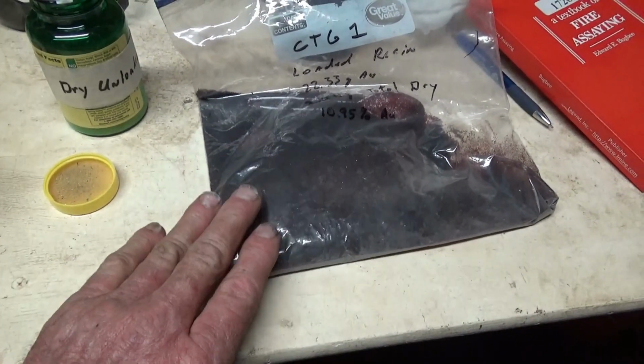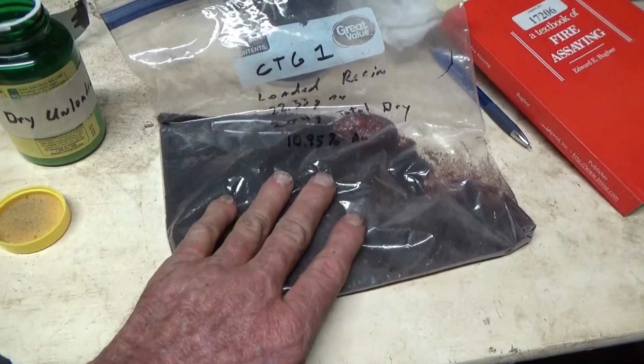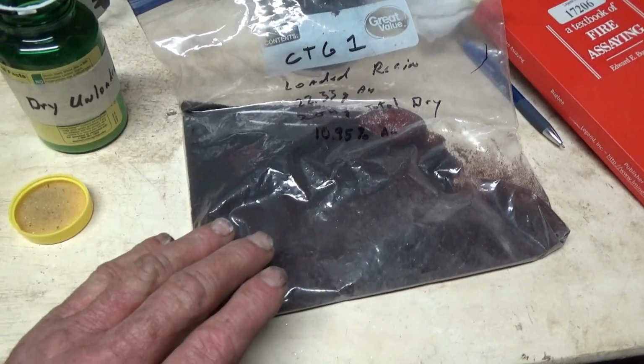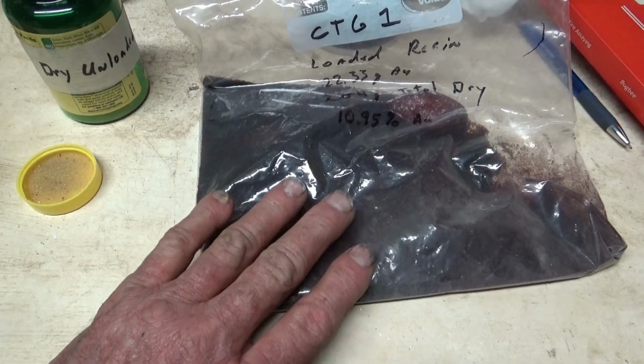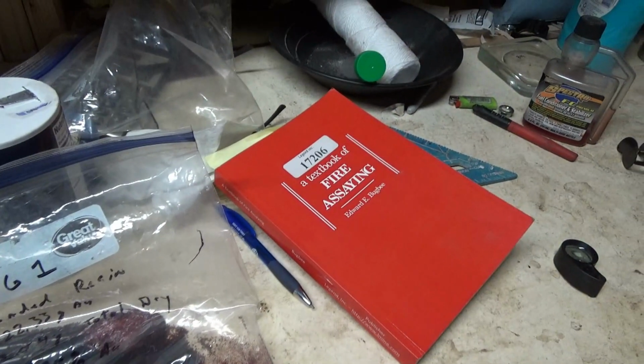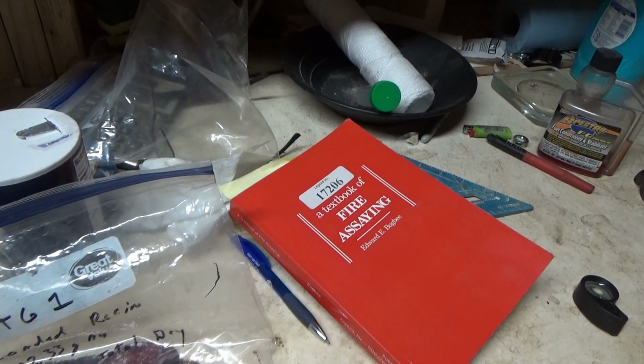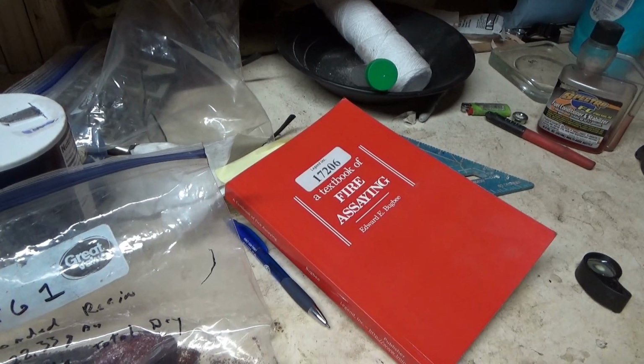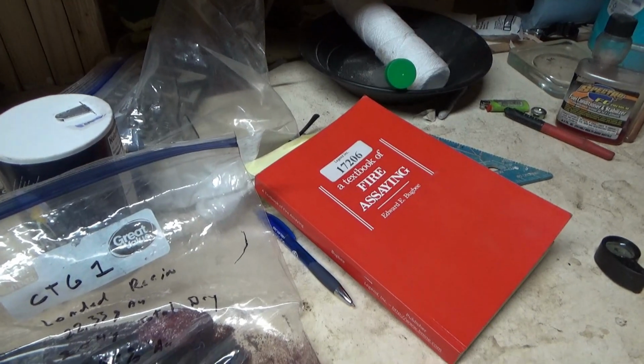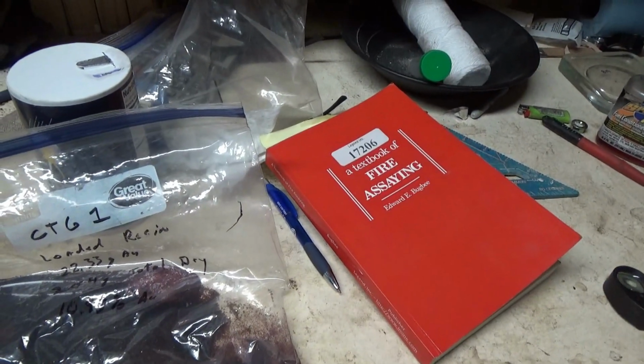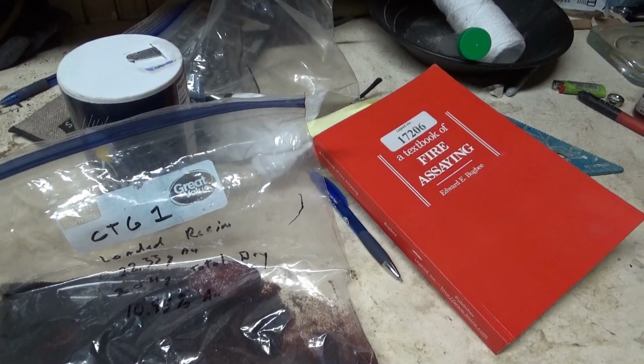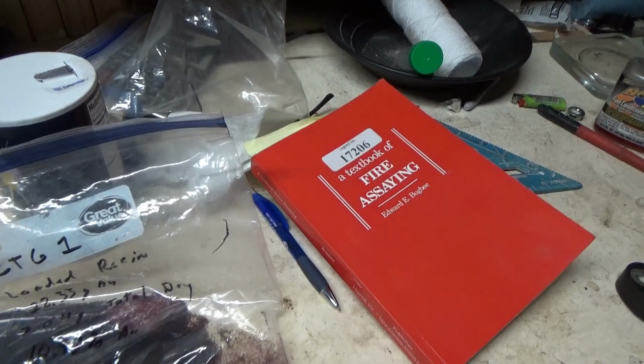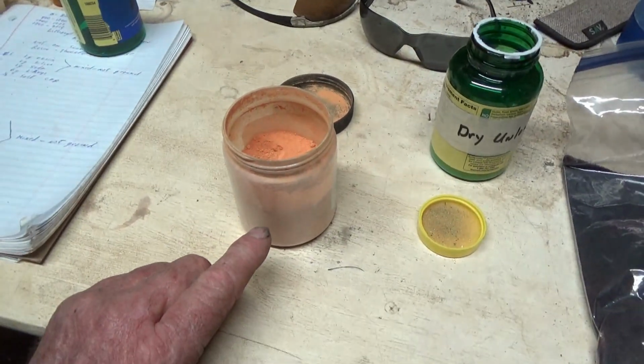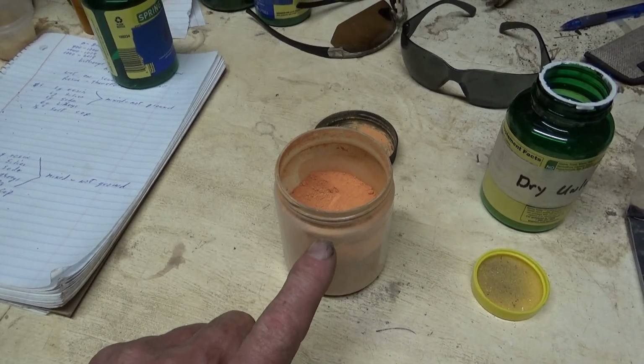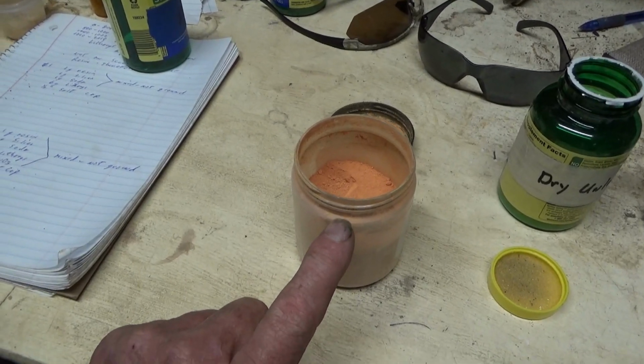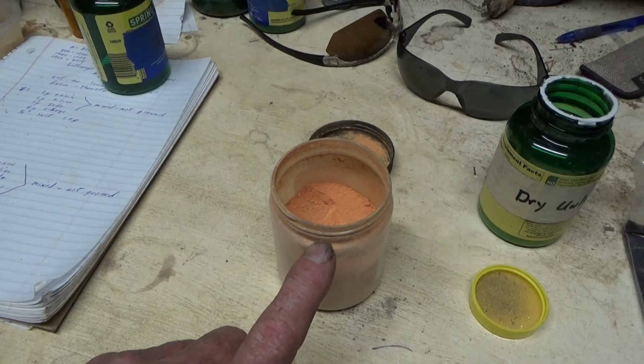Now, according to the calculations of the solution in, the solution out, and the weight of this, it should be running almost 11% gold by weight. So yesterday what I did was I used a standard flux formula in there for determining the reducing power of various materials, because different ores have different oxidizing and reducing potential, the ability to give up oxygen or to suck it out of other stuff, or the same reaction in terms of proton donor or proton acceptor. But anyhow, in fire assaying, you usually start with something called litharge. This is lead oxide. The idea is you want to reduce the lead oxide during the furnace to metallic lead.